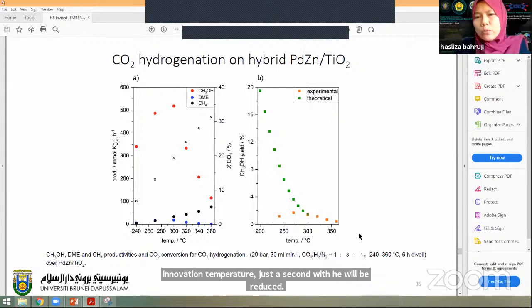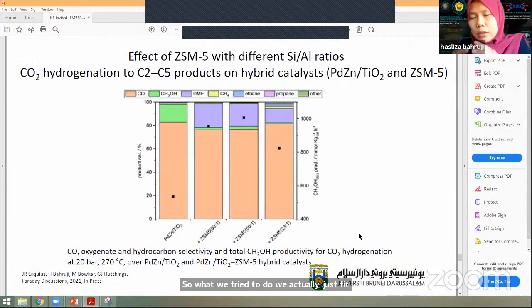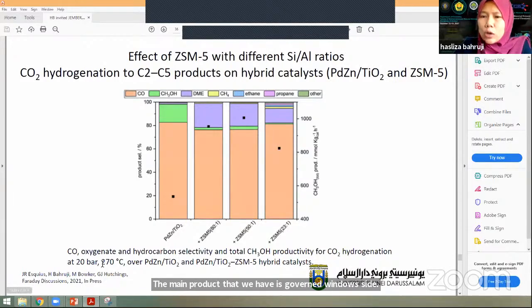So what we try to do is physically mix palladium zinc on titania as a catalyst with different types of ZSM5, at different silica to alumina ratios. So we have our palladium zinc titania here. The main product that we have is carbon monoxide, and then we have some methanol. Bear in mind, this is conducted at 270 degrees, which is not the ideal temperature for methanol production because of the thermodynamic restriction that favors carbon monoxide formation. So we have very small amounts of methanol, and then a tiny bit of DME.